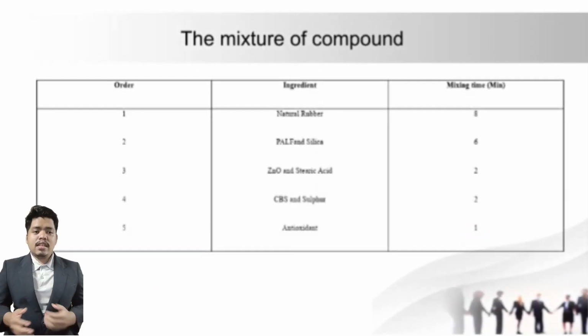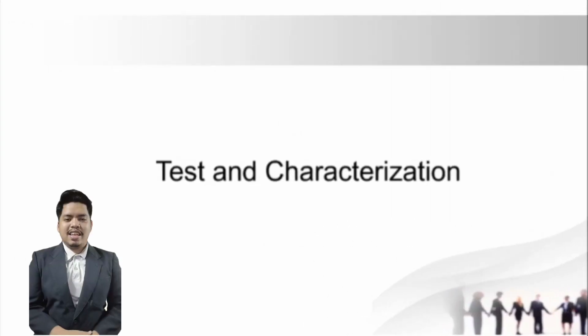Okay, so here is the ingredient needed for the mixture of the compound. Okay, firstly we need natural rubber, and then we'll need PALF and silica as a filler, and zinc oxide and stearic acid as activator and the co-activator agent, and we need CBS and the sulfur for cross-linking agent and the antioxidant to prevent the sample from oxidizing. Without wasting any time, let's move to the test and the characterization.